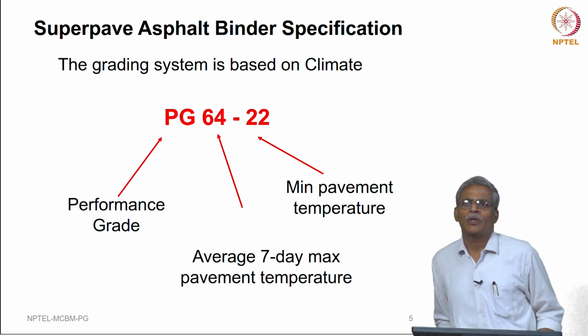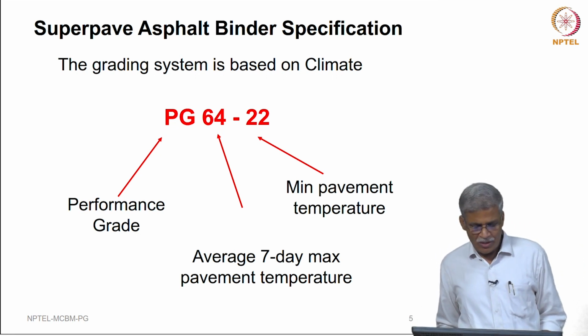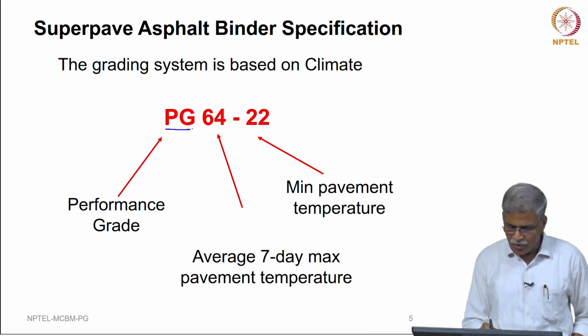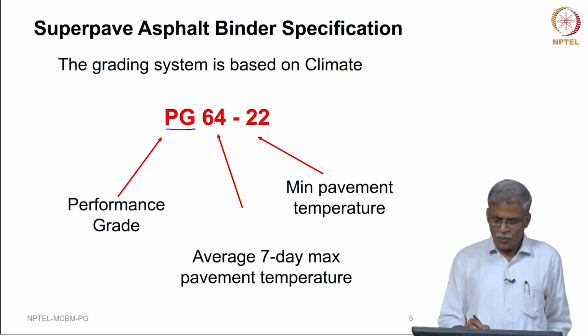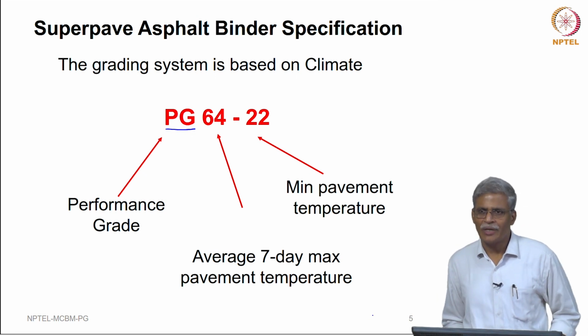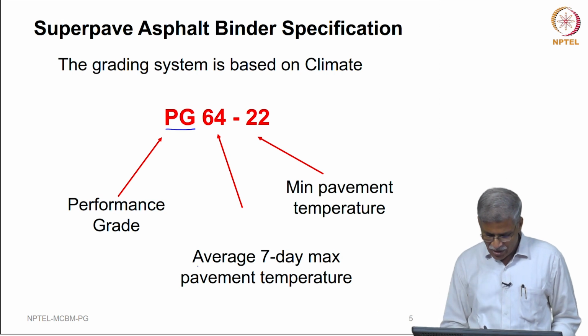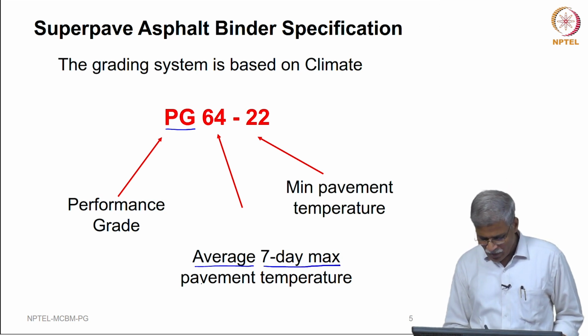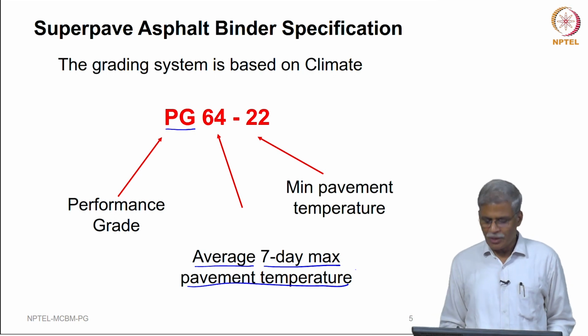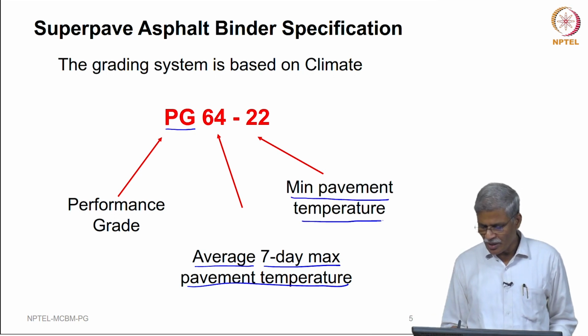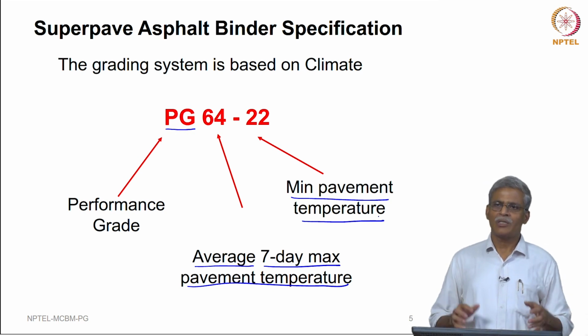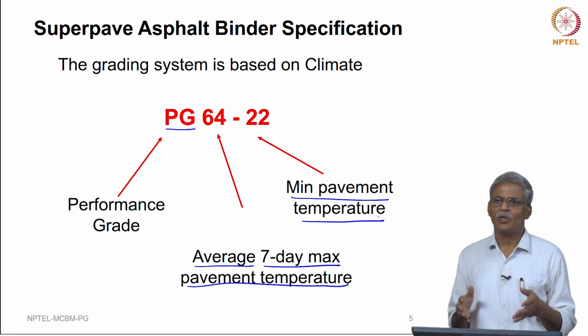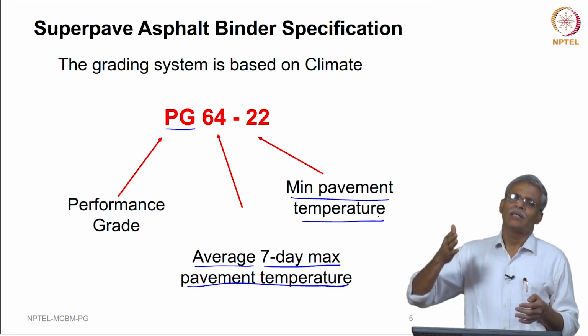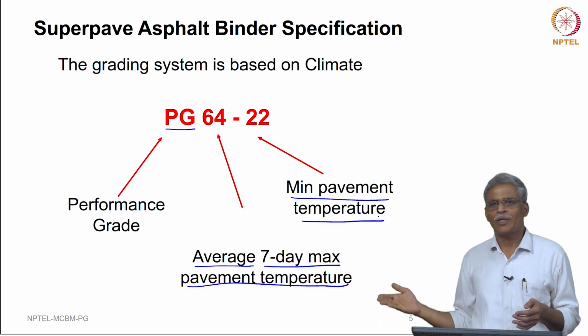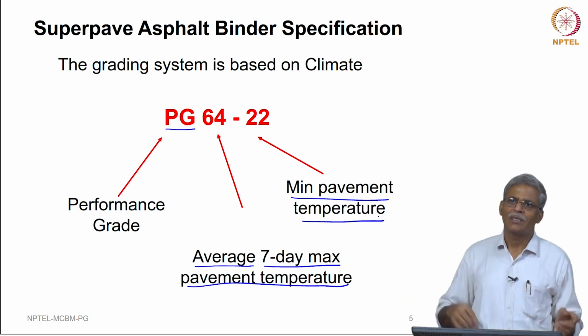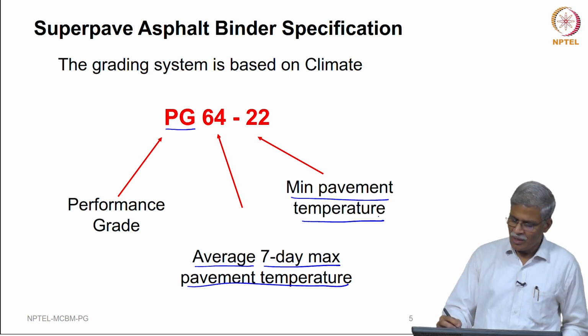So let us first introduce what is really called the PG specification. PG stands for performance grade, and you are going to see two numbers here, 64 minus 22. 64 stands for the average 7-day maximum pavement temperature, and minus 22 stands for the minimum pavement temperature. So what essentially this means is, if you use a binder in a geographical location that has 64 degree centigrade to minus 22 degree centigrade pavement temperature, this binder in essence will be resistant to